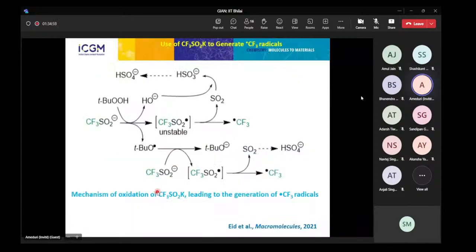So this oxidant, just like persulfate or, from the literature, this tertiary hydroperoxide, enables us to release this unstable intermediate, which led to the CF3 radical able to react with VDF. This was very well known, and we published that 2 years ago.